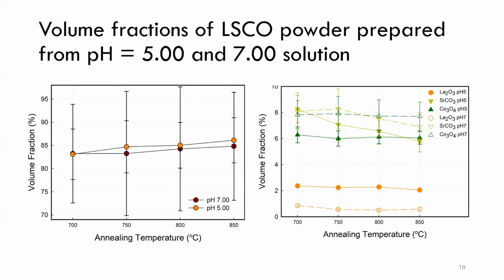Now, we compare the LSCO yield and the amount of impurity phases obtained from the two sets of samples. We see that there's slightly more LSCO yield in the set of samples prepared at a more acidic pH. This is also consistent with the decrease of the strontium carbonate phase. However, due to large uncertainty of the volume fraction of LSCO, we see no significant effect of the pH on the resulting LSCO phase yield. This is also true with the effect of heat treatment temperature.